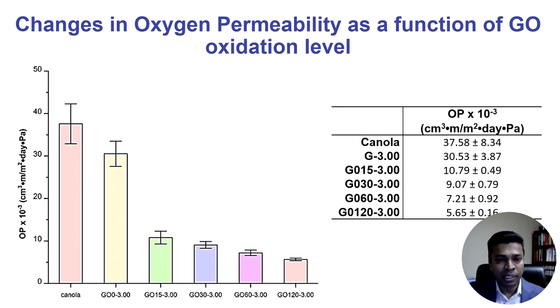I'm not going to go through all the results, but one of the things that we observe with the graphite oxide reinforced packaging films is an excellent improvement of the oxygen barrier properties, which is one of the key challenges that we have with most biopolymer based packaging materials. As you can see here, the reduction of oxygen permeability from the control canola film to the graphite oxide added films is over 600%, or a six times reduction in the oxygen permeability, which is an outstanding result.